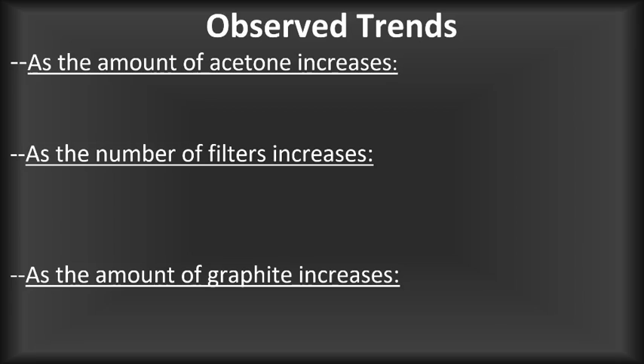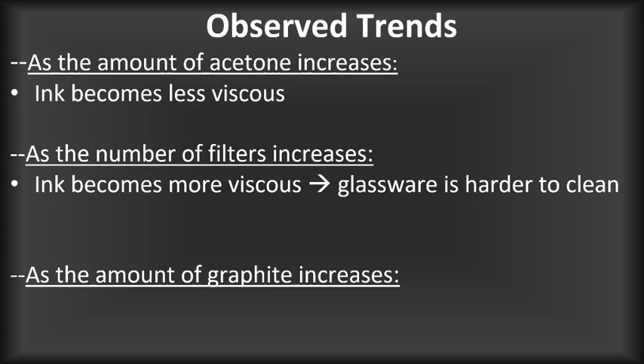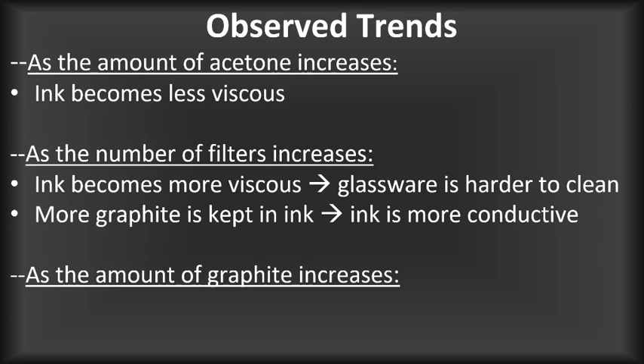As I said, extremely easy. And so I decided to further develop this by seeing what happens when I changed some of the amounts, like increasing the acetone, increasing the amount of graphite, and increasing the amount of cigarette filters. And I noticed that as I increased the amount of acetone, the ink became less viscous, which is honestly to be expected because you're adding more liquid. As the number of filters increased, the ink became more viscous, and for some reason the glassware was a lot harder to clean. And more graphite is kept in the ink.